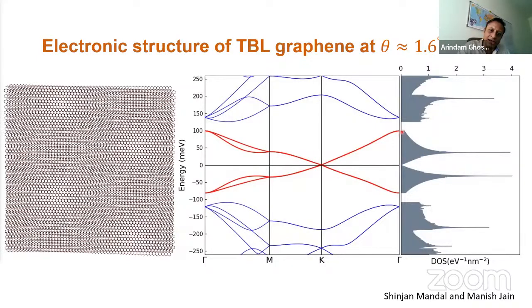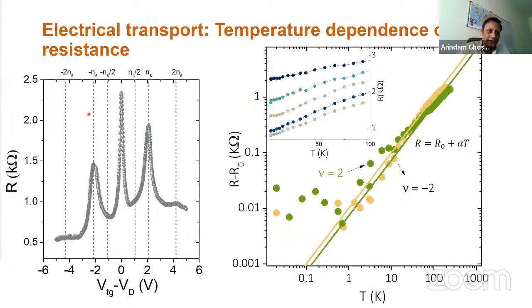You can see that density of states goes to 0 at 3 places. At this point, which is at the Moire gap, and this point, this is the other Moire gap on the other side, the hole side, and the charge neutrality point, which is here. Okay, so there are 3 different regions where the density of states goes to 0, which means that if I measure the electrical resistance of this system, I should get 3 peaks, and that's exactly what we get. You can clearly see that there are 3 different peaks. This peak corresponds to when the entire Fermi energy is at the Moire gap. So the band is completely filled from the electron side. This region is on the hole side entirely filled. And the center one is what we call the Dirac point.